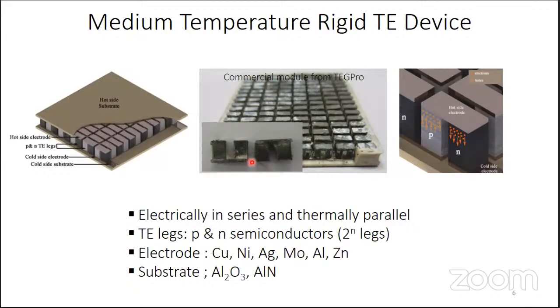Imagine some electronics, a low level of electronics, not microelectronics or super electronics, which has to work at a temperature of 400-500 degrees Celsius. Of course, the full leg will not be exposed to 400-500 degrees Celsius, only part of it. If this is the hot side, then at least a few millimeters from this joint, you will have elevated temperature. When you come to the cold side, you will have normal temperature, if not ambient, at least 50, 60, 70, less than 100 degrees Celsius. At least a small part of this material joined to this electrode is continuously exposed to very high temperature.